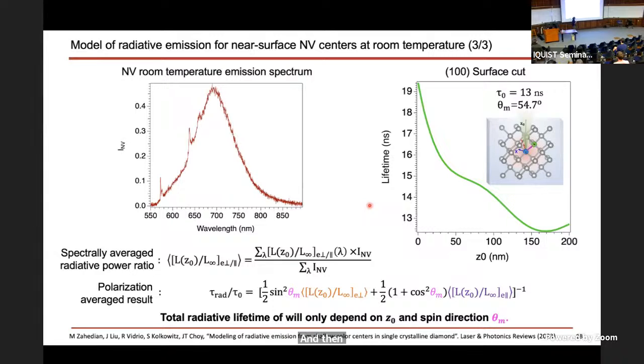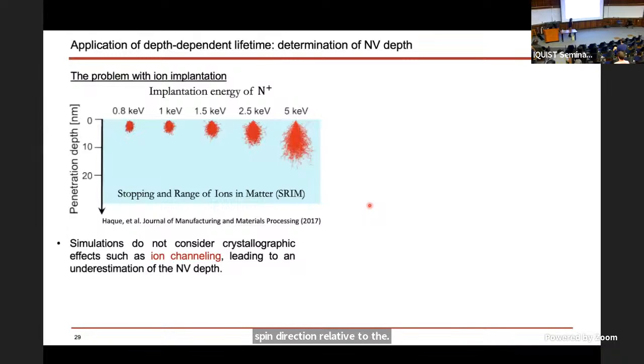So you have the radiative lifetime of the NV center at room temperature as a function of depth. And this is for 100-cut diamond. What we find is that it only depends on the depth as well as the spin direction relative to the surface normal. And so it would be great to experimentally validate this model.